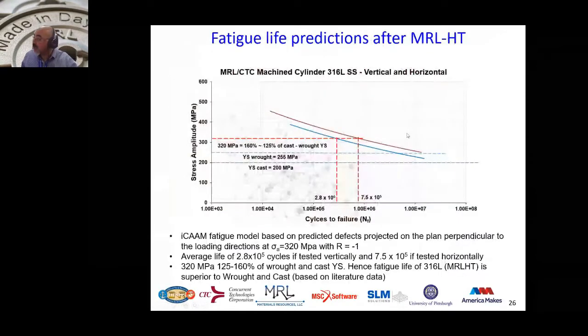One of the holy grails is related to fatigue, and this is where we are showing you the prediction that we have for the material, for the vertical and the horizontal. For this material, this is the machine, and when you are looking at the yield strength for wrought or cast, we are able to test above wrought and cast, about 125% higher than them. And we were able to predict 10 to the power 5 fatigue life at that stress amplitude, which is 320 megapascal, using the heat treatment and the build information that we provided to you.